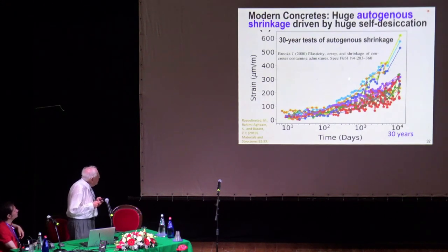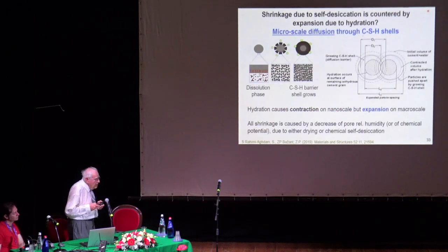I show here a picture from the only tests which are of long duration, most of them are a few months, but Brooks in England tested autogenous shrinkage on several different concretes. That's a scatter. You see it does not end with an asymptote, which is still assumed in the European code. It assumes it continues, goes on and on. It's faster than logarithmic, actually, as the data confirm.